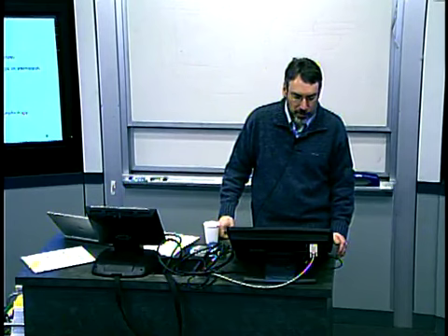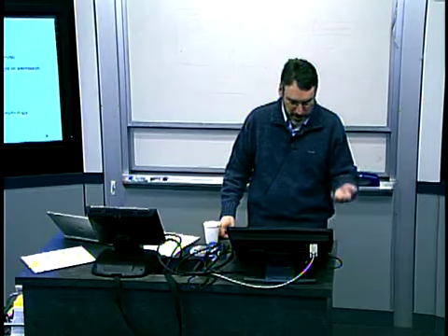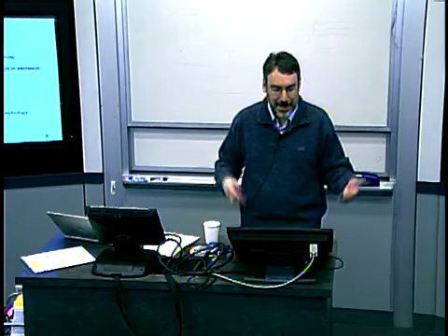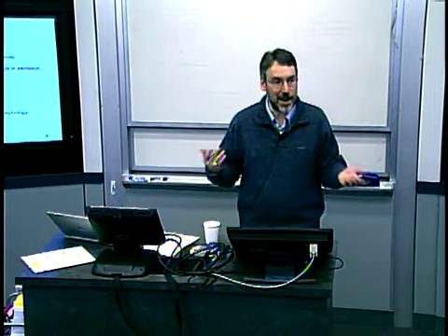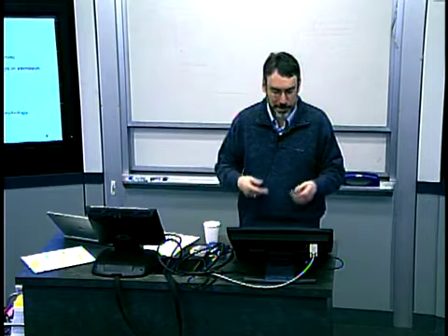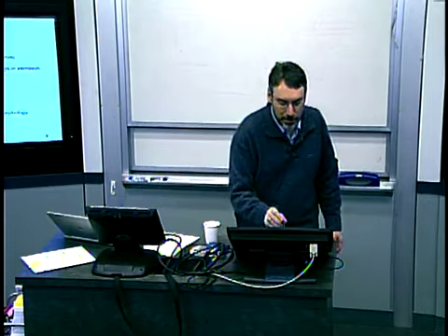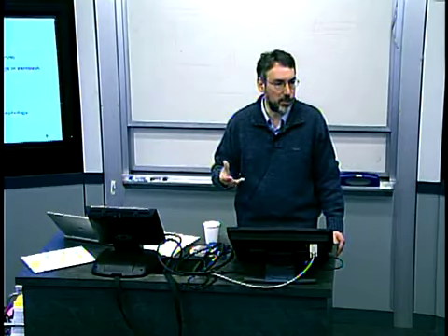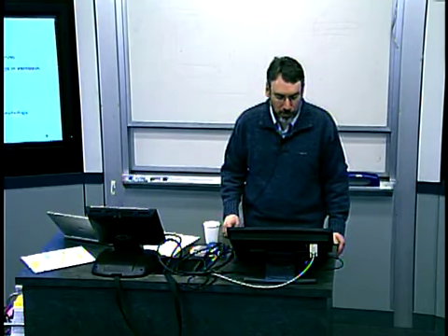So just to go through some of these parameters, many of them are pretty obvious, but a couple of them I want to explain a little bit more so that you have a good feel for what they are. Deposition rate, I think that's pretty obvious. Generally, you would like to have a fairly high rate. It's going to make the process time as short as possible, efficiency in the tool use, and so on. The paper mentions wanting to have about 500 nanometers a minute type rates with these processes. The resistivity value, or rho, here, generally you kind of want a low resistance or a low resistivity film.